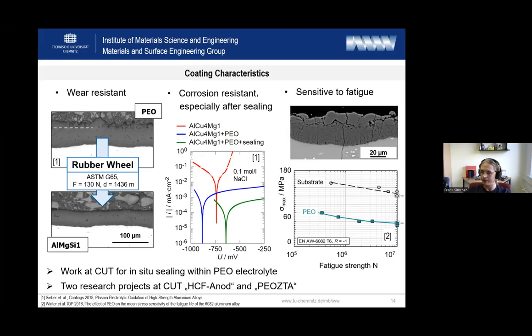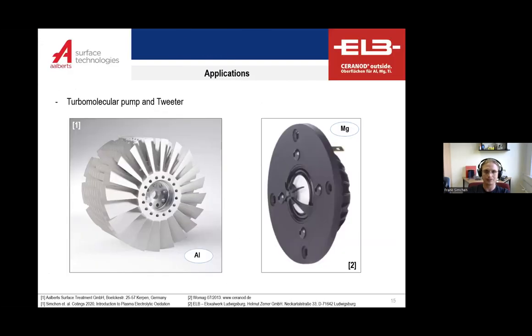But I also want to state that the sensitivity against fatigue is just a fact which should be taken into account. And it's not an exclusion criterion, because if you design your component well, then you can use PEO coatings also in applications of strongly alternating mechanical stresses. And here we come to our first application. This is the rotor of a turbomolecular pump, which is used in the ship industry to transport corrosive gases. And this pump is turning with some 10,000 rounds per minute. So it's really fast. And such a component should not be so heavy, just to make sure that it is not jumping outside of your system.